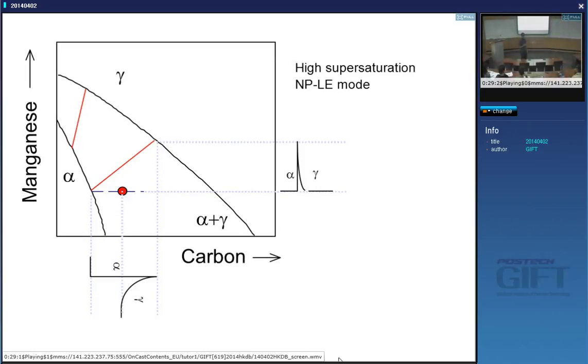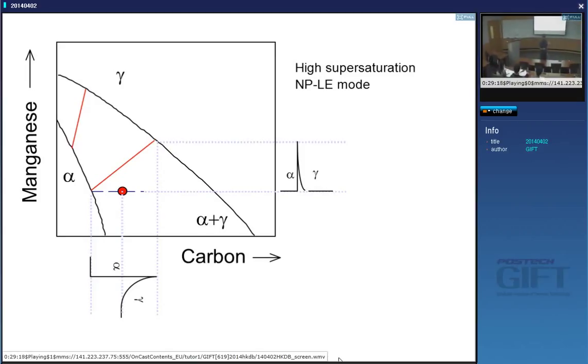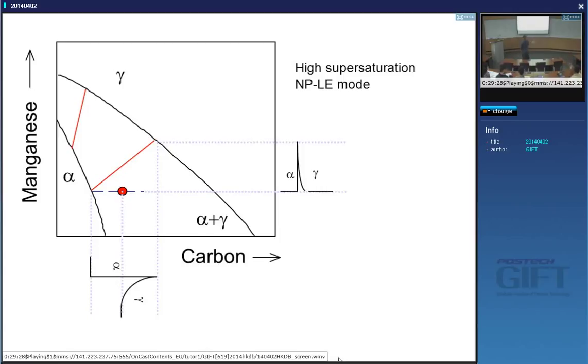Let's imagine what would happen if the thickness of this spike becomes physically meaningless — say it becomes one atom. Our condition is only that the carbon diffusion flux must match the manganese diffusion flux, and their diffusion coefficients are eight orders of magnitude different. So why should we have zero manganese diffusion? That's why I say negligible partitioning local equilibrium — negligible means there is still some partitioning, otherwise you would not get local equilibrium.